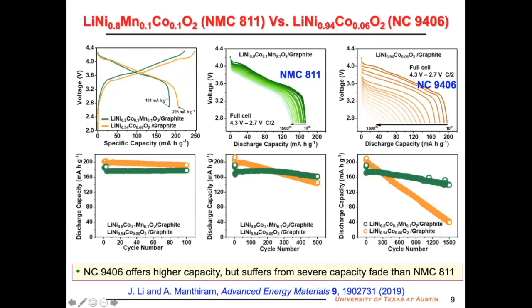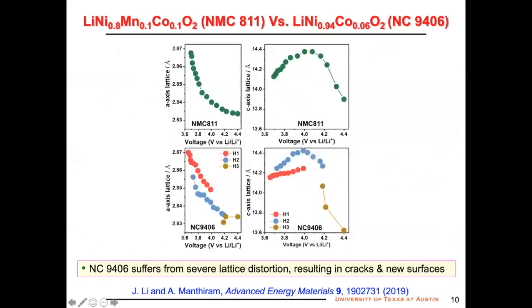If you look at the cycle life, if you really look at a large number of cycles, like 1500 cycles, then the 94% nickel fares much worse compared to 811. So now we need to understand why.